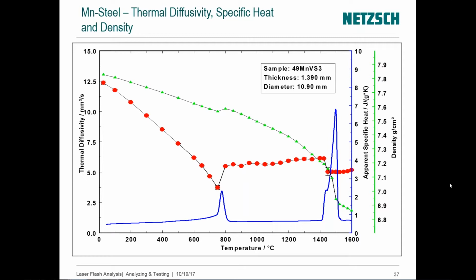Again, it's very important. If the sample is not changing, if the sample is stable, there is no reason why the diffusivity should change. The tiny little heat or energy being introduced into the specimen will not change its thermophysical properties, will not change its diffusivity. And furthermore, the first measurement will be done at one time, and then there will be a certain lapse of time after which the second measurement is made. So by then the sample is back in steady state, so there is no reason why the diffusivity should change. So no problem regarding that at all. Hopefully I've been clear on that for that answer.